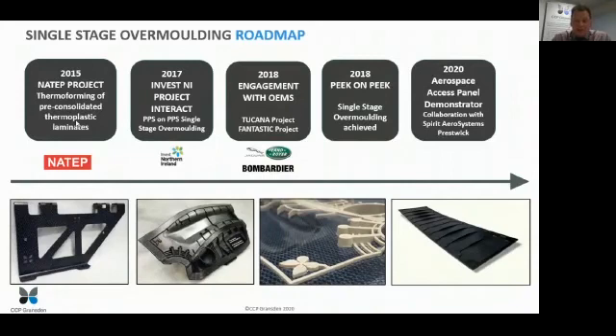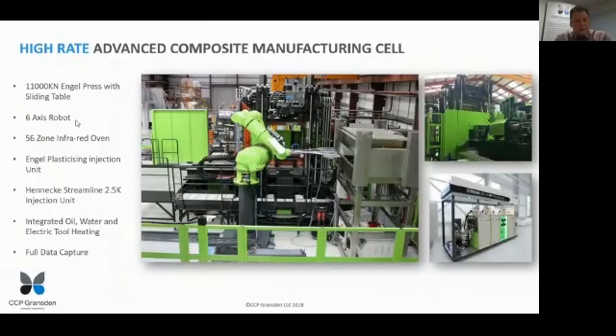In 2018, not solely focused on single stage overmoulding, but we did enter into 2 large programs, one with Jaguar Land Rover and another with Bombardier, focusing on these high rate technologies that we have. So we didn't stop there, we've kept going. In 2018, we managed to do PEEK on PEEK, the third picture across at the bottom. That was on the same tool demonstrator, but there was a lot of things which we still needed to perfect and develop in terms of the manufacturing process. In 2020, we were able to move forward and manufacture an aerospace representative component, and that's been working with the aerospace primes to develop that, make sure it's customer focused.